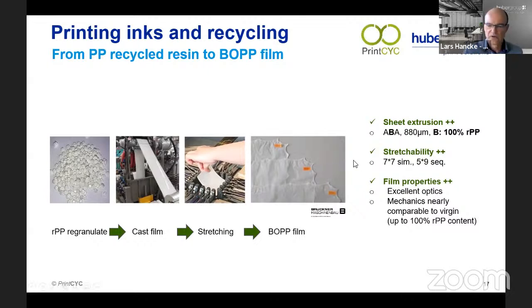And we were able to successfully convert the regranulate into the biaxially oriented film with excellent stretchability, even with a high amount of recyclate and film properties that are almost the same as for virgin material.